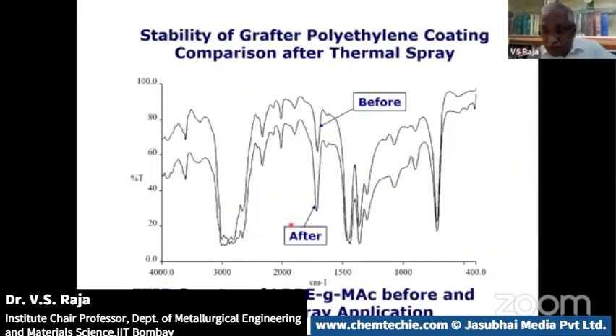Now again, when you do a thermal spray, it should not decompose, right? If it decomposes, everything is gone. So you look at the IR spectrum before and after, and see that yeah, they're looking good. There's not much of a problem, and there's no decomposition. Of course, we need to optimize the temperatures, we need to optimize everything. Otherwise, you can burn. I mean, obviously, you can burn.